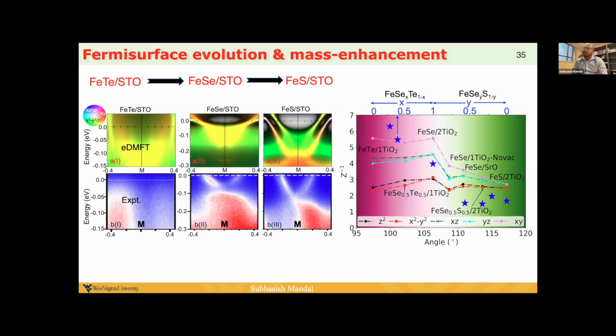I agree with you, except for the hybrid functional. We actually did hybrid functional. It turns out to be a disaster even for bulk. It shows a gap even in certain bulk, because there are parameters in hybrid functionals, and one should not just trust them blindly. We actually tried two different types of hybrid for simple sodium or potassium metal, and we saw that it was the worst, even worse than LDA for metals.